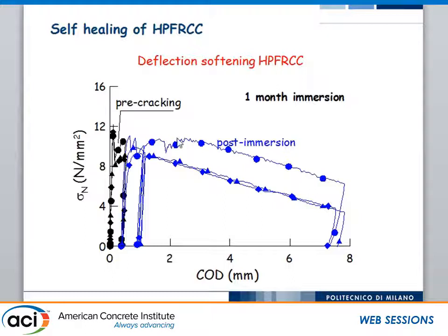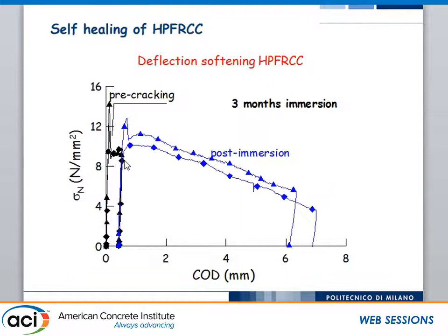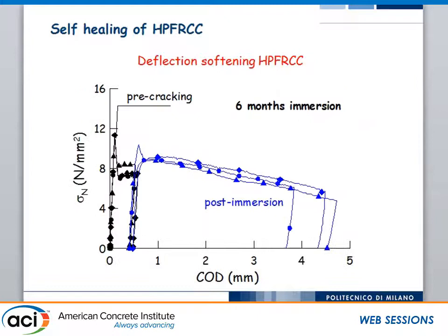the failure test. So we could see that after 1 month, basically, we got back about the same stress level that we had before pre-cracking. But if we go to 3 months exposure, when we pre-cracked and unloaded the specimen to put it in water, we went to this. You could see that we pre-cracked at this level, and so when we tested back after 3 months, we went up to this.